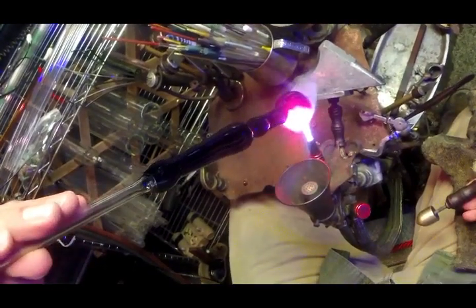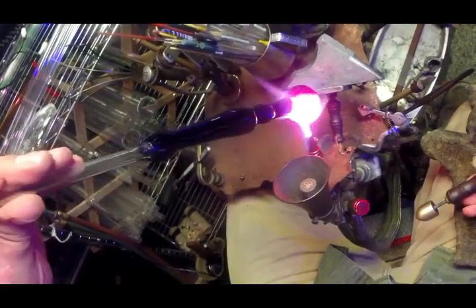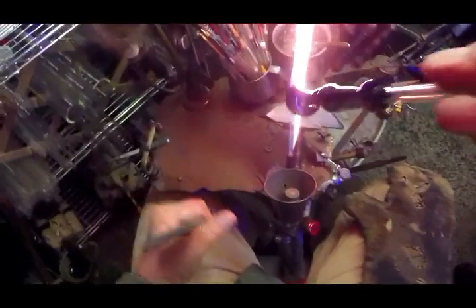Basically, you just want the handpipe hanging straight down into the flame so that you're not tilting it to one side or the other. It will droop before it's ready to push if you're too uneven. So I'm blowing into it while pushing it down, and that helps the glass to not collapse but rather come up and fold around the push.